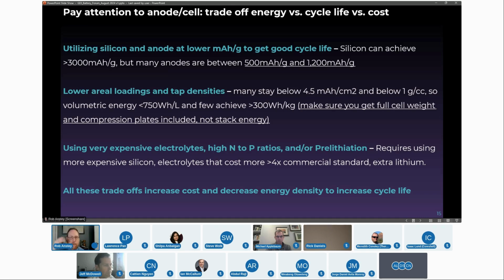It does 3 things for you. First, you don't run your silicon 0 to 100 anymore. Let's say you pre-lithiate 30%. Now you're only running your silicon 30 to 100, and most people don't run to 100, they run to 90. So now you're only running your silicon 30 to 90. Of course, that's going to dramatically increase your cycle life. The second thing it's going to do is give you more lithium inventory. Now you've got double the lithium inventory. So you don't go to 80% state of health anymore. You go to 60% state of health or 50% state of health. But it looks like 80% state of health because you're digging into your extended range, so to speak.